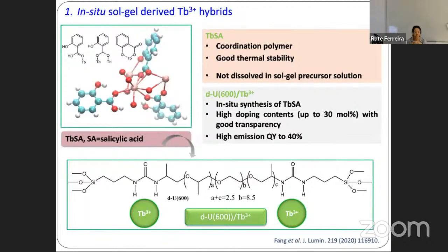One of the known problems associated with the incorporation of optical centers into hybrid or polymeric matrices is typically the low solubility of some of the complexes. Thus, to mitigate this issue, we use in situ synthesis, which was exactly the case that I'm showing to you in this slide. This is the case of a salicylic-based terbium coordination polymer that is not soluble in the diureasil precursor. Thanks to the interaction between the diureasil and the complex synthesized in situ, we obtain a green luminescent material with a quantum yield up to 40%.